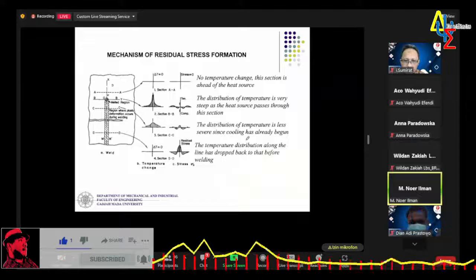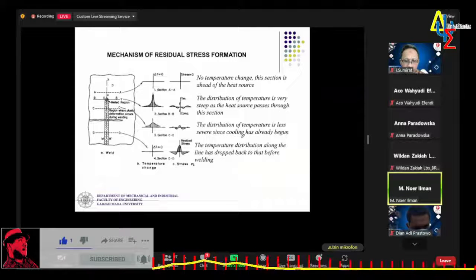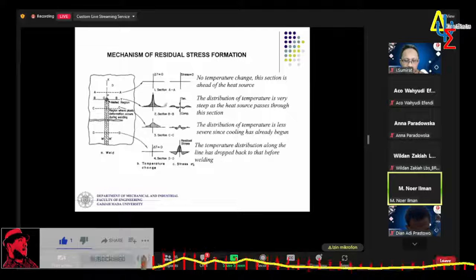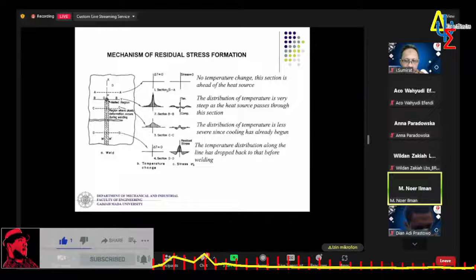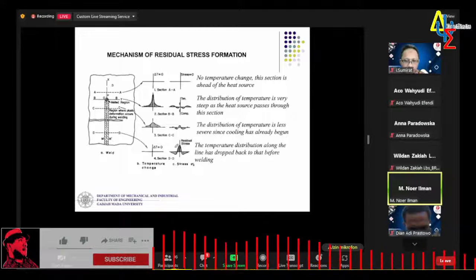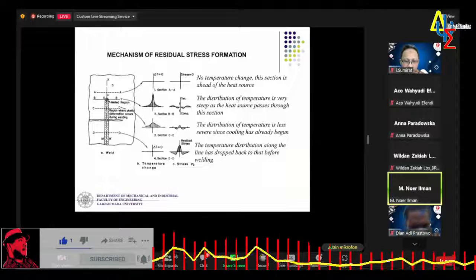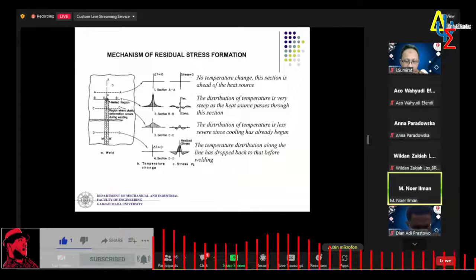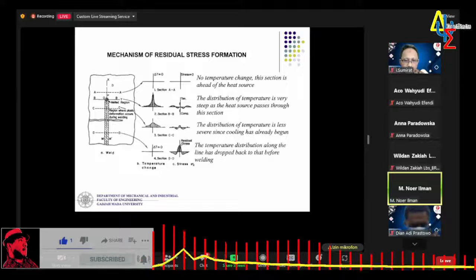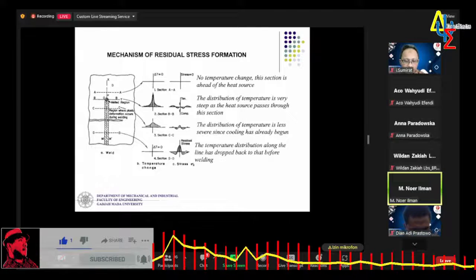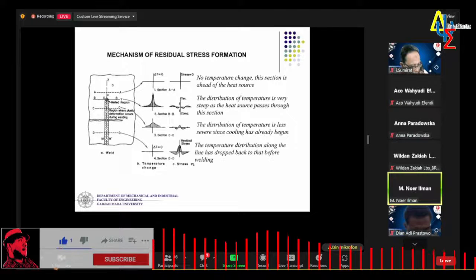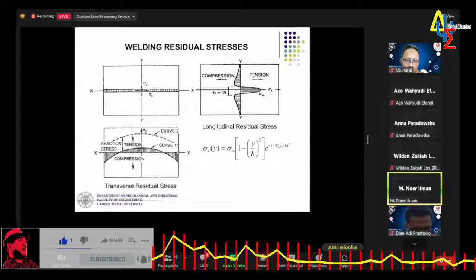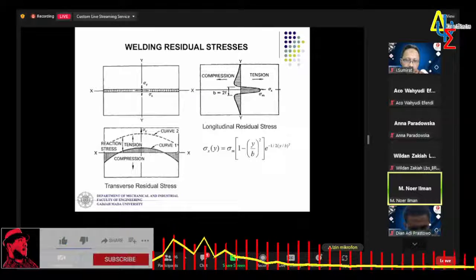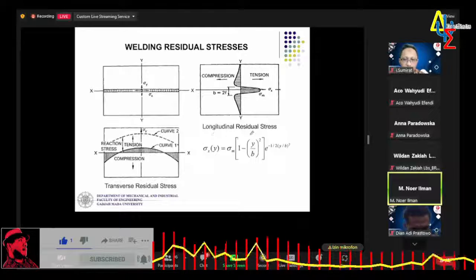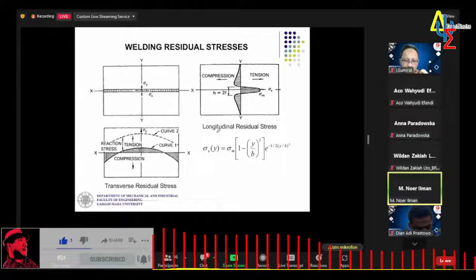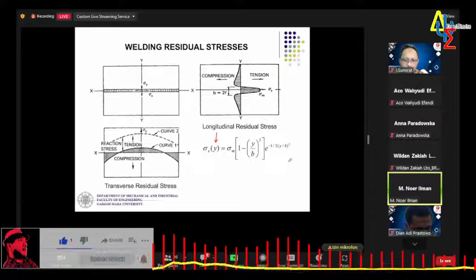And this is the mechanism of stress formation. Due to local heating, it produces residual stress where the weld metal and the region near the weld metal reveal tensile residual stress, and to compensate for this, the region away from the weld produces compressive residual stress. And you can see that residual stresses can be divided into two, which are longitudinal residual stress and transverse residual stress. And this longitudinal stress can be represented by this equation.